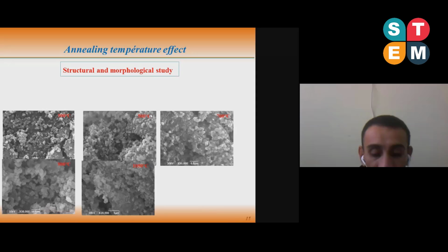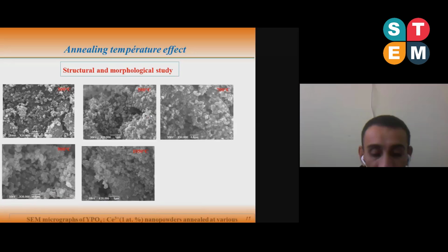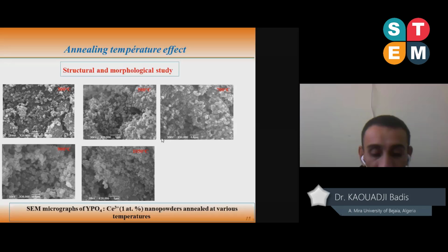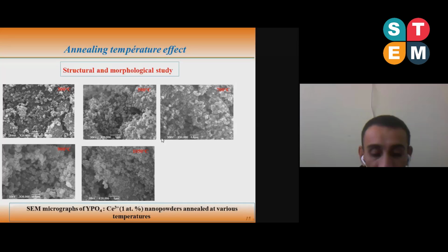This figure shows scanning electron microscopy of yttrium orthophosphate nanopowder annealed at various temperatures. The SEM images of the sample show that the obtained powder consists of large quasi-spherical particles with varying sizes, ranging from a few nanometers to several hundred nanometers. The bigger particles are composed of tens of smaller particles with an average diameter of 30 nanometers. This powder has agglomerated particles due to the effect of annealing temperature.